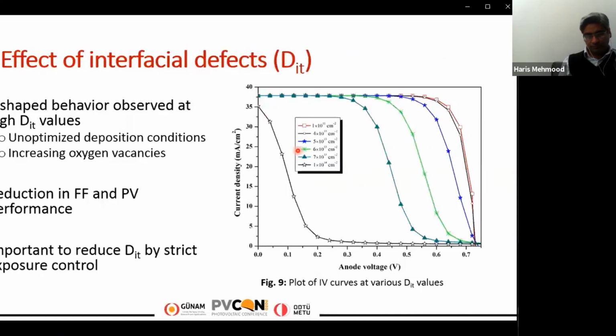Similarly, we have also studied the effects of the interfacial defects on the photovoltaic performance of the device, and we have seen that the S-shaped behavior was observed at higher interfacial defect values. And these high Dit values can be approximated by the unoptimized deposition conditions as well as the increase in oxygen vacancies. So with the increase in the oxygen vacancies, the Fermi level of the tungsten trioxide will be pushed towards the conduction band, and that will lead to the decrease in its work function values.